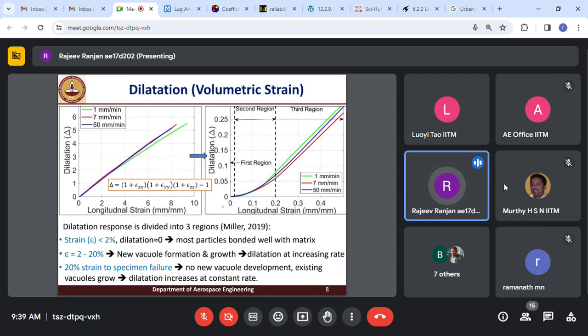The first region was where dilatation was nearly zero, that was up to 2% of the strain. So we said that in this zone, there is no detachment of the solid particles, there is no vacuole formation. In the second region, the dilatation was increasing at an increasing rate. In this region, vacuum holes are getting formed because of the strain in the material, and there are some existing vacuum holes which formed in the beginning, I mean after 2% strain, and they are growing in size. So two phenomena, the growing size of the vacuum holes as well as the formation of new vacuum holes, are happening in the second region. That's why dilatation is increasing at an increasing rate.